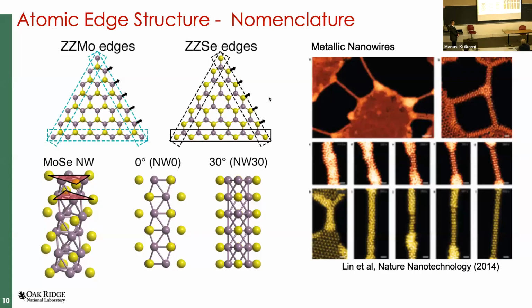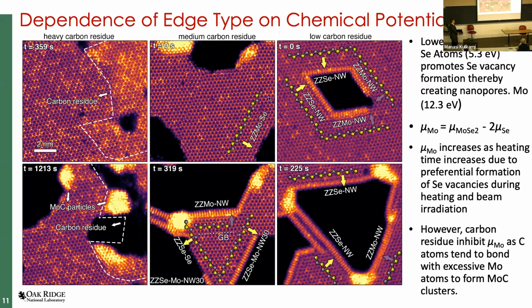So if you hear me use the terminology nanowires, it's basically this atomic reordering process that's an agglomeration of moly and selenium in this case. And then we might have a case where it's a different orientation, how it's viewed at the atomistic scale. Okay, so just keep that in the back of your mind. So what I wanted to point out here is just because we were able to see this at the atomic resolution, we can infer a couple of things. From theory, we know that if you hit these types of materials with an electron beam, the chalcogen atoms are really easy to knock out, right?